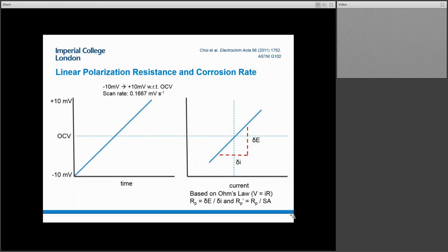And we can essentially use Ohm's law, where we can determine what is the resistance of the system at that point in time. And if we do this at regular time intervals, then we can create a figure that highlights how the resistance of the system is varying. And in fact, we often normalize it based on surface area. But again, just as I said at the beginning about the bulk material situation, that also has the challenge that your surface area is evolving and how you decide to model that.